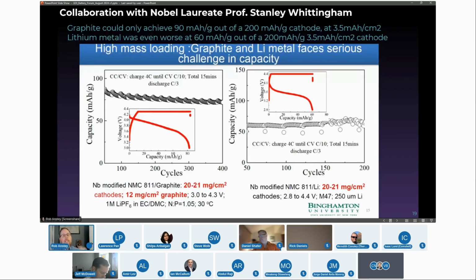So what we basically got now is we said, let's see what third-party data looks like. So we worked with the co-inventor of the lithium-ion battery, the Nobel laureate Professor Stanley Whittingham, and we sent them anode. We said, let's run it against graphite and lithium metal in fast charging. So this is specifically a 4C charge until C over 10 cutoff, 15 minutes, and a discharge of C over 3 every single time. No rest periods, no C over 20 refresh, none of those games.